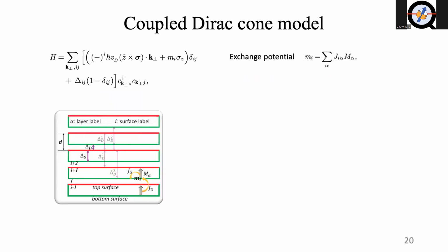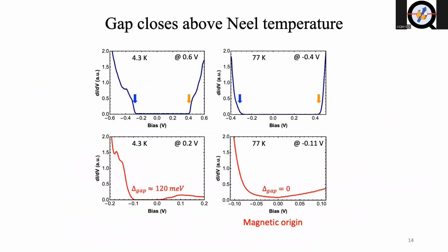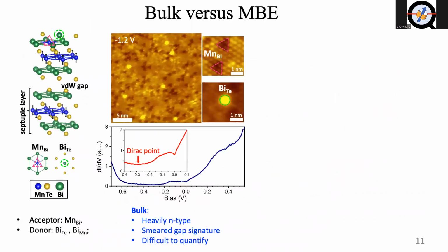Okay, so I guess your question is whether we can get access to the manganese tellurium layer, right? Yeah. Okay, so first of all, we can take a look at the structure. You can see the van der Waals gap is between the tellurium and tellurium layers, right? So naturally, that means if you cleave, you will always cleave there. That's right. However, I think some MBE groups also reported that they have seen the manganese tellurium layer. But then the manganese tellurium is just manganese tellurium; somehow it doesn't sink into the middle of the BT. I didn't see a very systematic study for the MT, but you can form a small patch of MT that happens to not sink into the middle of the BT.